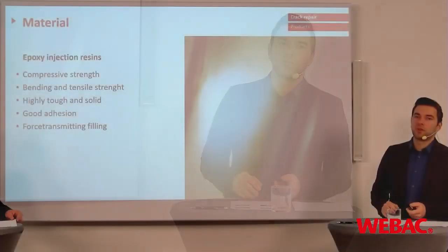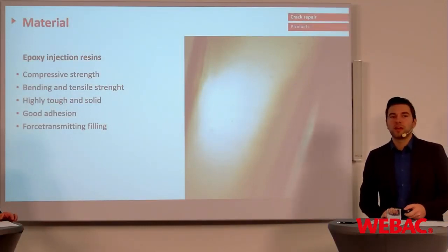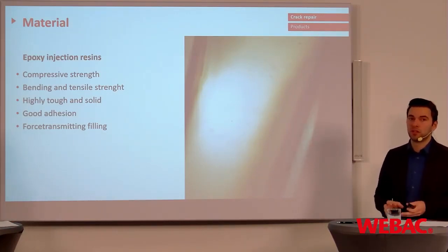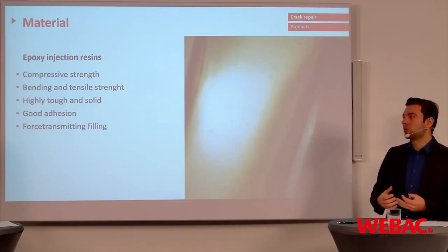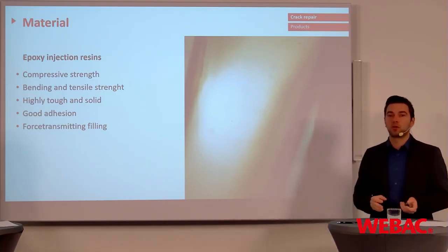The epoxy injection resins have a high compressive strength, a high bending and tensile strength. They are tough and solid, and they have very good adhesion to concrete edges. Therefore, due to the high mechanical properties, the epoxy injection resins are designed for force-transmitting filling, meaning you glue the broken concrete parts together and give back the strength. The mechanical properties, the compressive strength of these materials, are higher than standard concrete. So we are talking about a strength of 40 Newton per square millimeter or even higher.